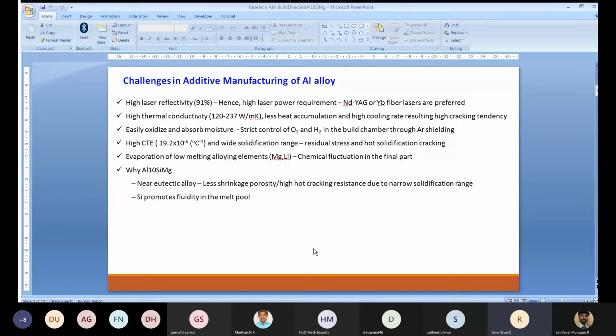And aluminium has another issue, a high CTE, that is coefficient of thermal expansion. This is a problem when you rapidly heat and cool. It will induce thermal stresses due to non-uniform thermal expansion and contraction. And second, aluminium alloys mostly have a wide solidification range. You have a liquid, then a range of temperature where both solid and liquid are there, then you have a solid. In the solid and liquid region, because of the wide solidification range and the high cooling rate, you will generally form complex dendrites and interdendritic regions. The region solidified last will be devoid of metal to be filled there, causing solidification cracking at the end during solidification. We call it solidification cracking or solidification shrinkage porosities.